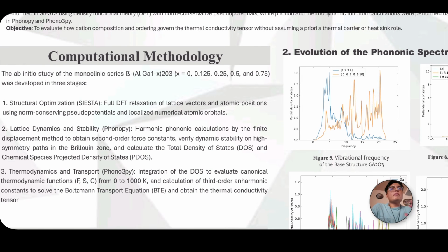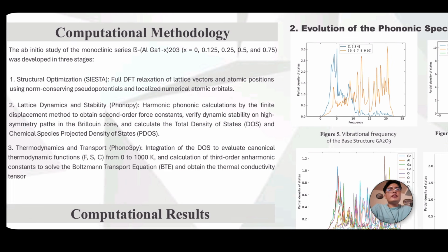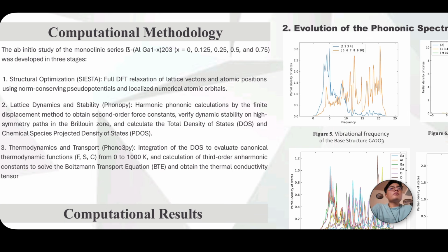Next, we will discuss the method used to perform this analysis, which consists of 3 fundamental stages. In the first stage, structural optimization with SIESTA, we completely relax the lattice vectors and atomic positions of the structures using density functional theory calculations. For the second stage, lattice dynamics and stability with Phonopy, we obtain the second order force constants to verify the dynamic stability of the crystal and calculate its vibrational density of states.